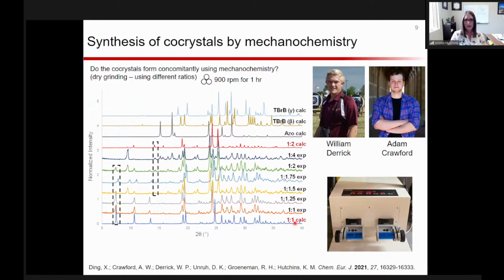What we have here at the very bottom is the calculated powder pattern for the 1-to-1 form. And then up here in red is the calculated pattern for the 1-to-2 form. The top 3 patterns are the individual components, so this would help us figure out if we just had physical mixtures. Azopyridine has 1 form, but the tetrabromobenzene actually has a couple of known forms. And then what I have here labeled in black letters are all the experimental data.